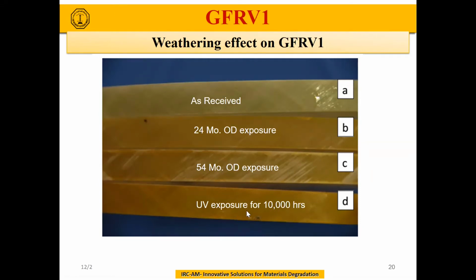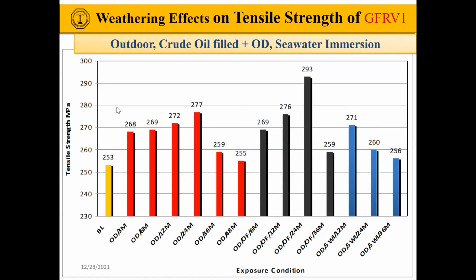And here for UV exposure at 10,000, which is equivalent to about 36 months of outdoor exposure. We looked at the tensile strength of these vinyl ester specimens after 3 months of outdoor exposure, 6 months, 12 months, 24 months, and for outdoor, and then the oil-filled pipes exposed to outdoor conditions, and the seawater immersed pipes also after 12, 24, and 36 months. As you can see here, this is the baseline. This is the as received pipe.